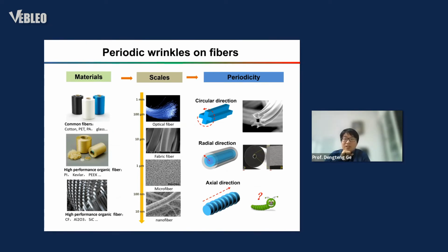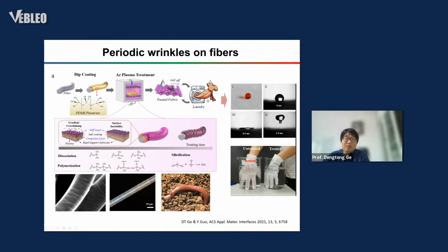Otherwise, we make some wrinkles on the fibers, because on the fibers they have many periodic structures. This one has a periodic structure in the circular direction, and this one in the radial direction. However, there's no periodic structure across the axis direction. To generate this earthworm-like structure, we coat the PDMS precursor on the PET fiber and use plasma to treat the surface. By controlling the intensity and the energy of the plasma, we successfully made the wrinkle-like structure on the fibers.